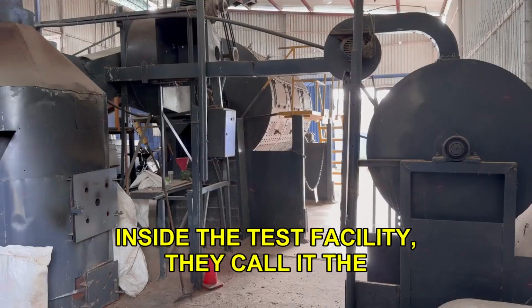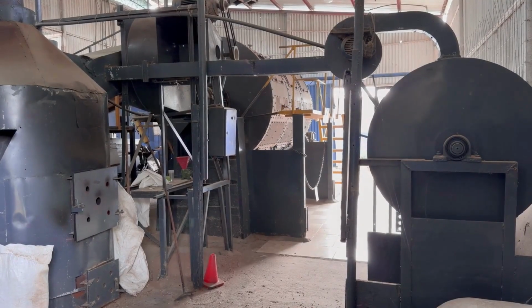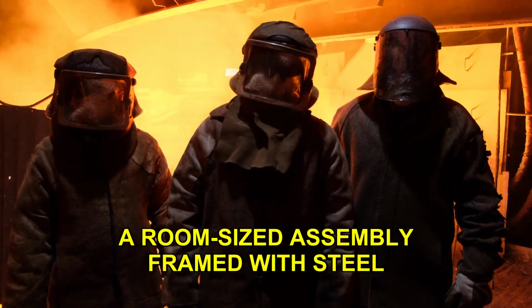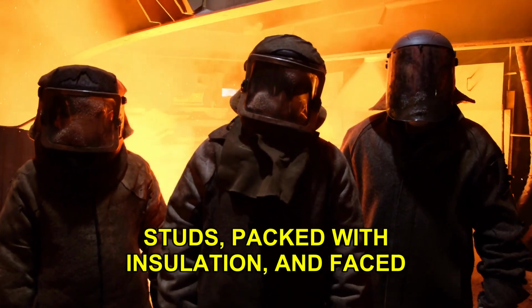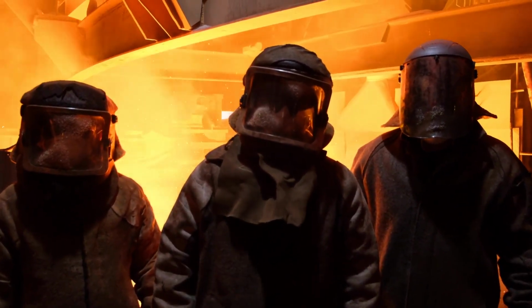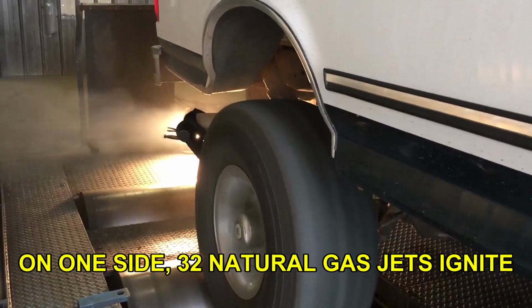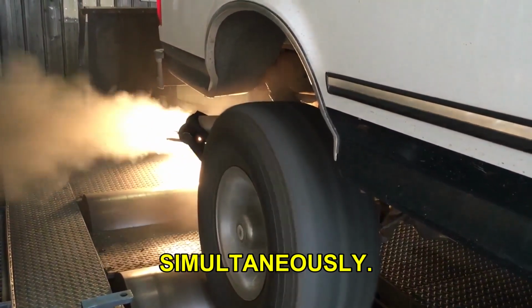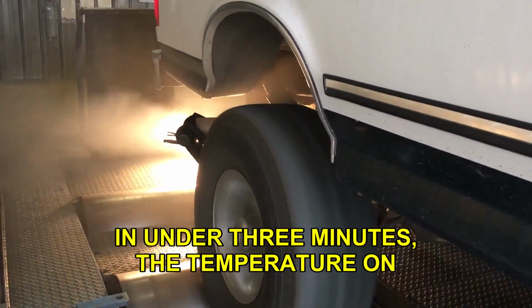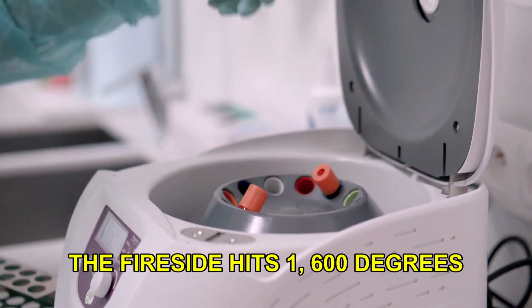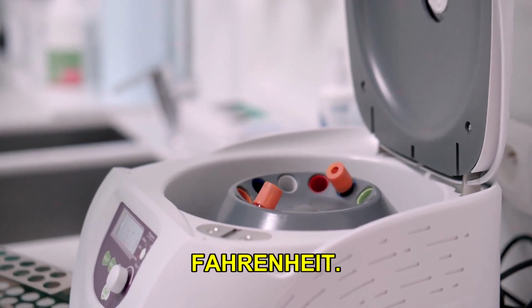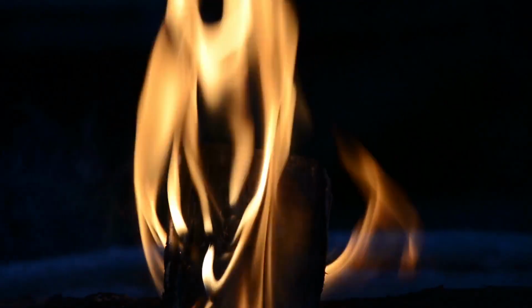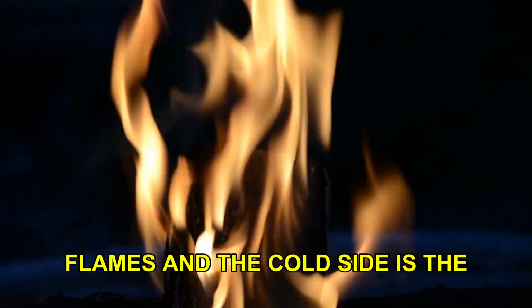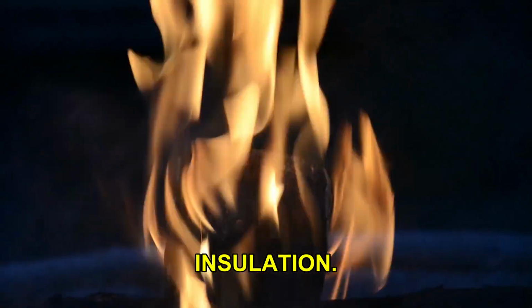Inside the test facility, they call it the burn wall. A room-sized assembly framed with steel studs, packed with insulation, and faced with drywall. On one side, 32 natural gas jets ignite simultaneously. In under 3 minutes, the temperature on the fire side hits 1,600 degrees Fahrenheit. The drywall crumbles. The studs begin to glow. And the only thing standing between the flames and the cold side is the insulation.